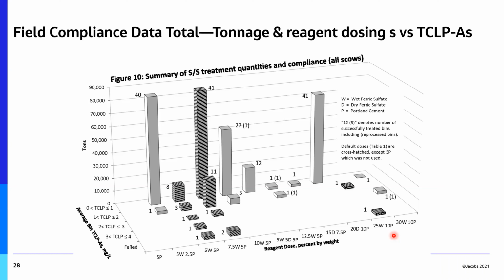But before that transition, these are the doses that were initially recommended from the treatability study, which are the crosshatched, and the others are, you know, as we gained more information and got more comfortable with our dosing strategies, we looked at a lot of intermediate and other doses, especially this 20% dry with 10% Portland, which was one of the best mixes that we ended up working with across the project.